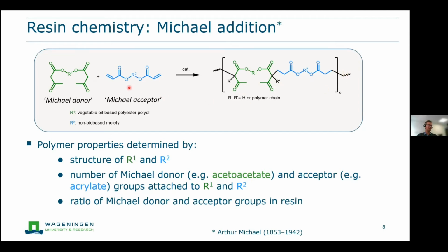In this case, for this particular application, the Michael donor was based on a vegetable oil-based polyester polyol, and the Michael acceptor was a non-bio-based moiety. And we found that the polymer properties could be tuned by changing the structure of R1 or R2, or changing the number of Michael donor or Michael acceptor groups, and also by changing the ratio in which the two reactive components are mixed.